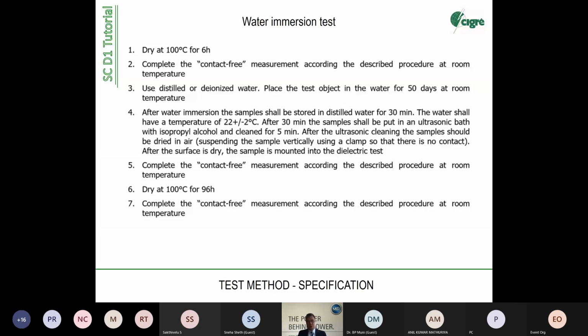Complete the contact-free measurement according to the described procedure at room temperature. Dry again at 100 degrees for 96 hours, and you can check whether this is a reversible effect or whether it is irreversible. So this was actually not the plan, but hopefully, or fortunately, we did this, and it gives a real good insight into what's going on with these materials.